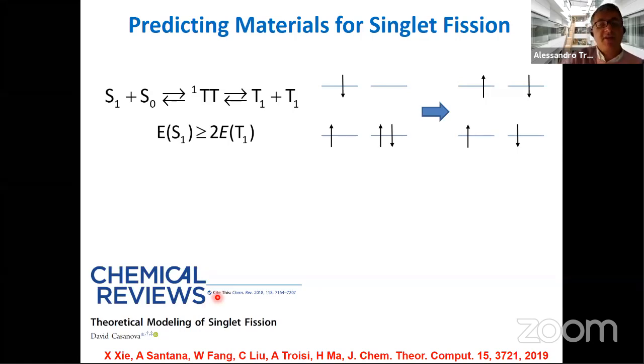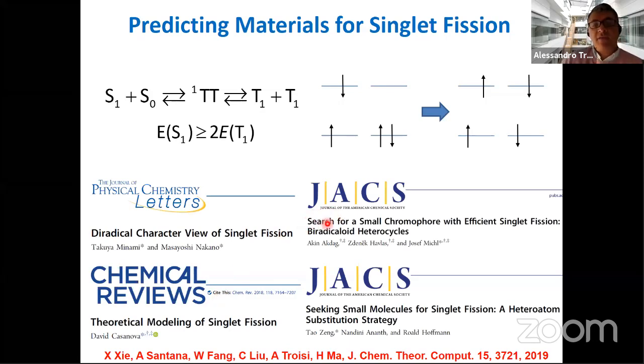So if you look at the literature, many of the highly cited papers talk about mechanisms or strategies to search for materials with these properties. So materials with a very low-lying triplet, such that twice the energy of the triplet is less than the energy of the singlet. So seeking, and one of the main ideas is to build or search for molecules which have a diradical character, because the idea is that the diradical molecule has a triplet energy very close to that of the ground state singlet, and therefore may be suitable for this type of material.